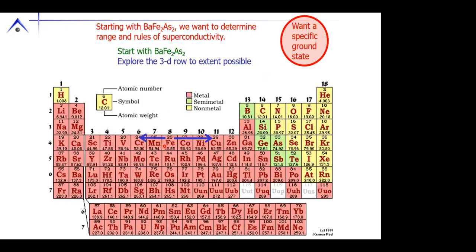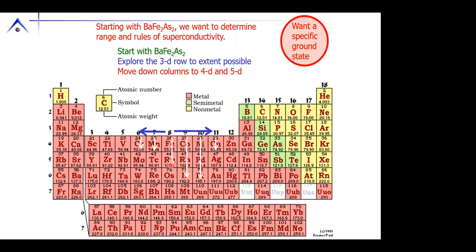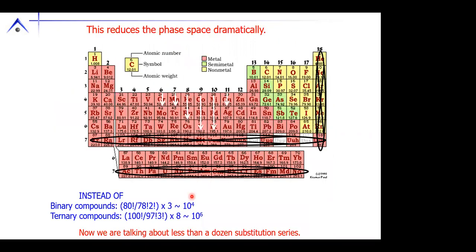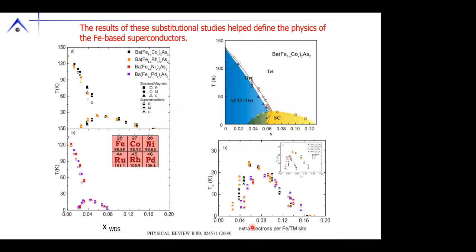We can start with iron, and we can then say, fine, let's see what happens as we substitute in various 3D transition metals. And we don't need to limit ourselves to 3D. We can go down to 4D or even 5D. The importance of this is that instead of having millions of random compounds, we're now talking about a dozen or less substitution series. This is finite and tractable. And indeed, what we were able to do then is by looking at, for example, cobalt, rhodium, nickel, and palladium substitutions, establish the rules for the road for this type of superconductivity.